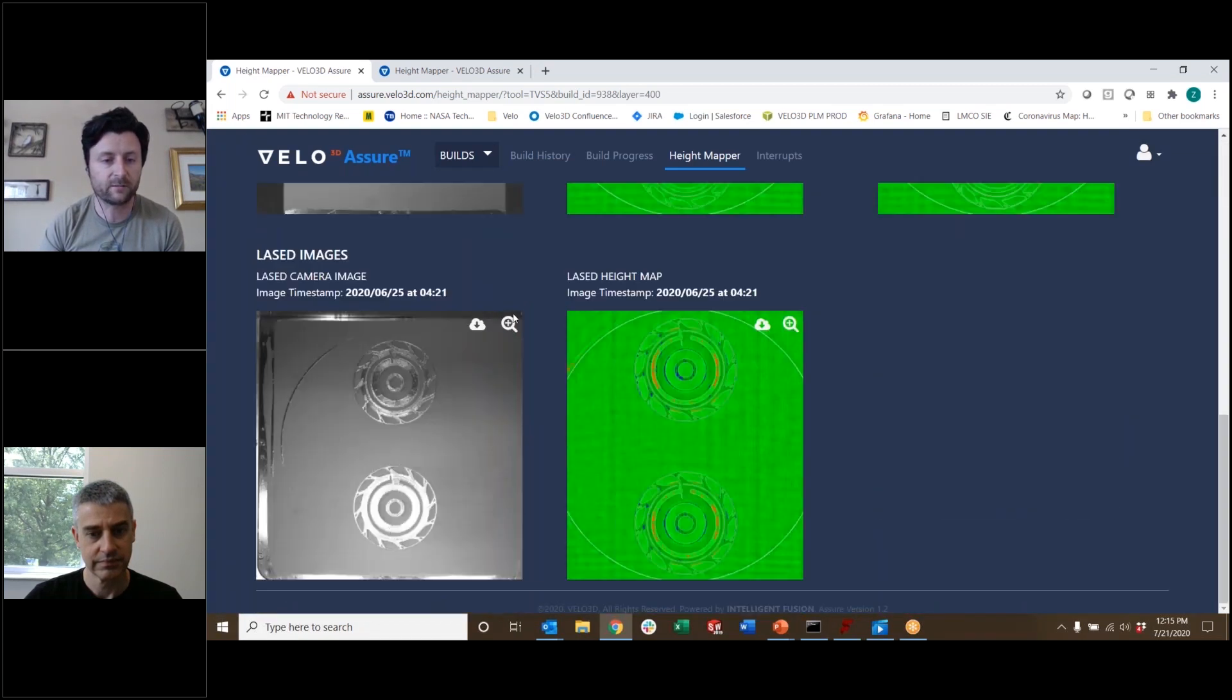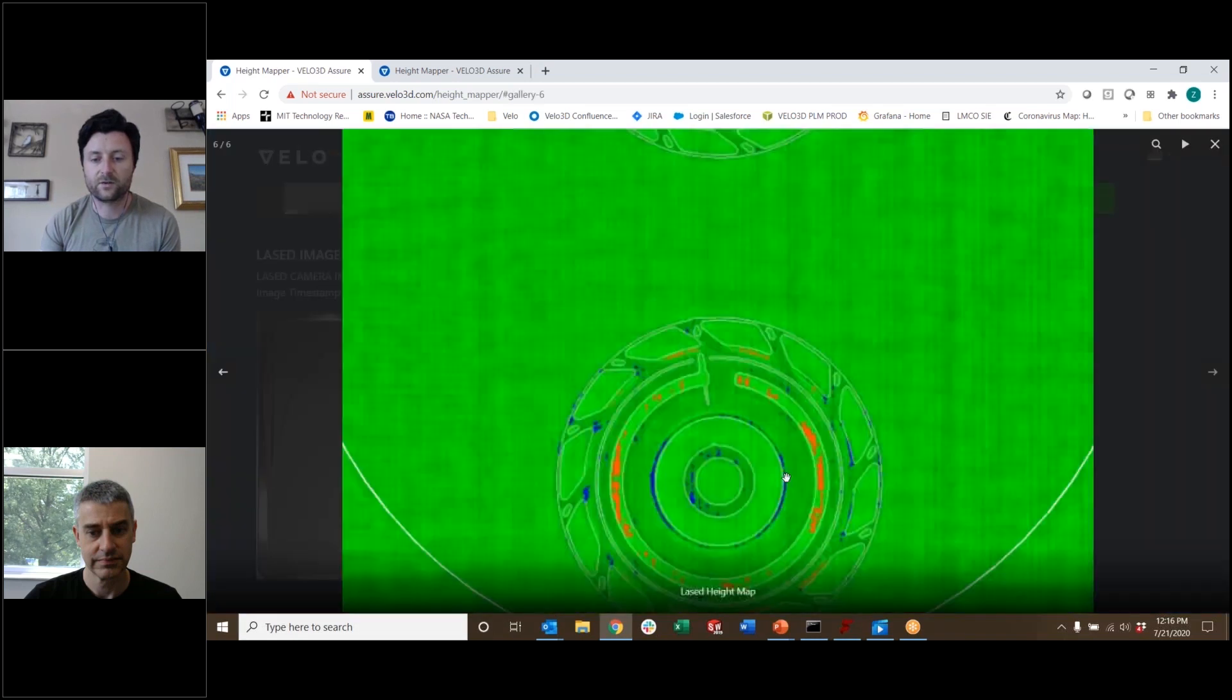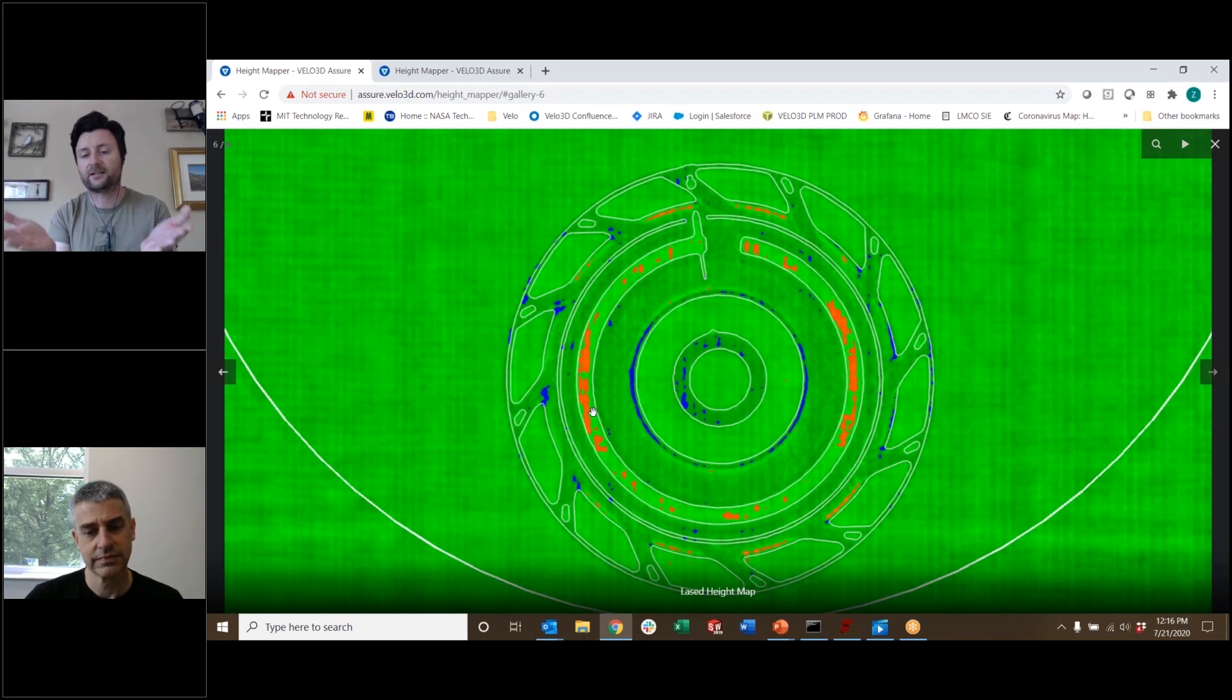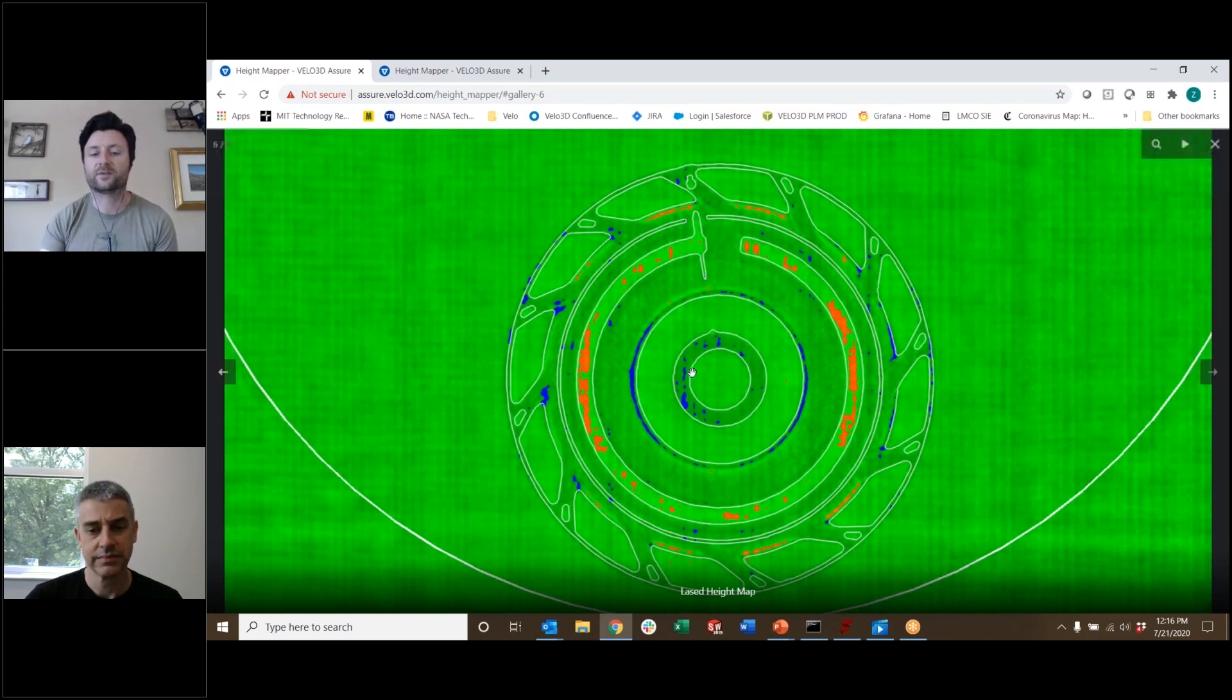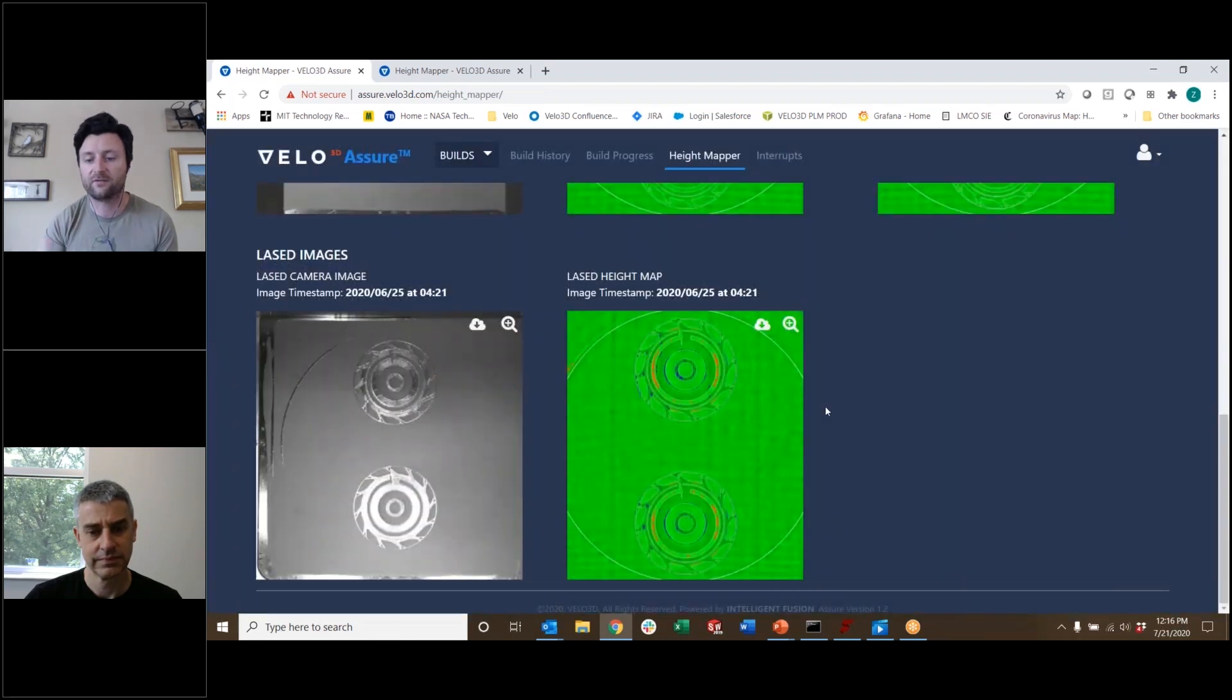You can see here the lased image. So this is the actual photo taken from our camera system built into the machine. And this gives you an idea of what you're printing at that moment. And then you have the data that's interpreted from that scan. And so you can see red here is slightly protruding and blue is slightly below the powder bed. Generally, if you see red, you'll see it on surfaces that are very overhanging and it tends to protrude a little bit through the powder bed. And that's one of the nice things about the non-contact recoater that we have is that you can actually tolerate some amount of protrusion and continue the build. So while this may look alarming, this is actually something that is generally pretty common when you're building overhanging structures. Whereas the blue tends to be more in the core of the material where you're solidifying and just reducing the volume as the powder turns into solid metal.